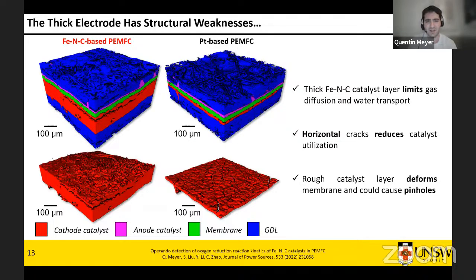You only have cracks the other way, in the thickness, that allow gas to diffuse. They're very good for water transport. So two very different environments. Another thing you can actually see if you look closely: the surface of the Fe-N-C catalyst layer is very rough. That's because of the way it's deposited. You can't avoid agglomerates. Whereas on the other hand, platinum-based catalyst has a very smooth surface.